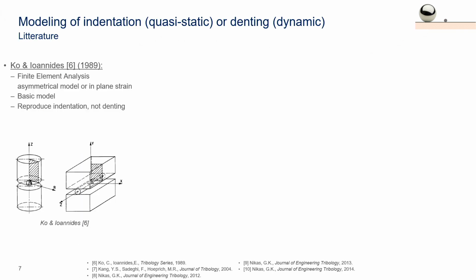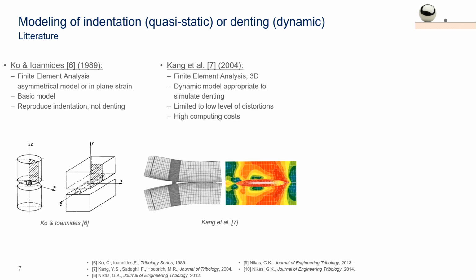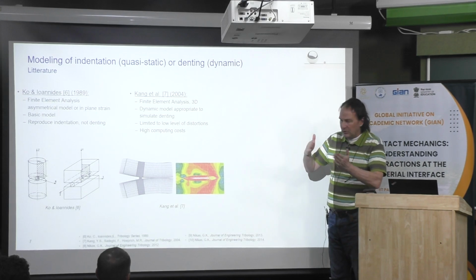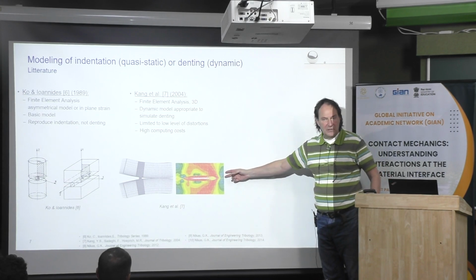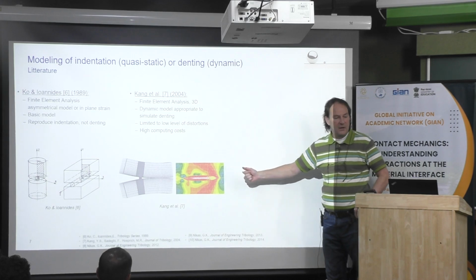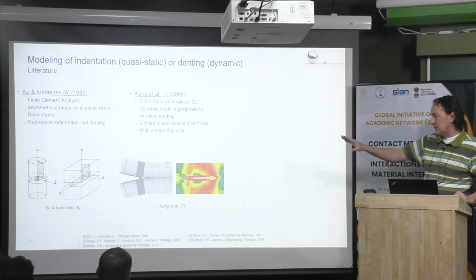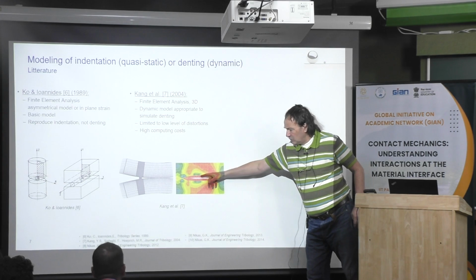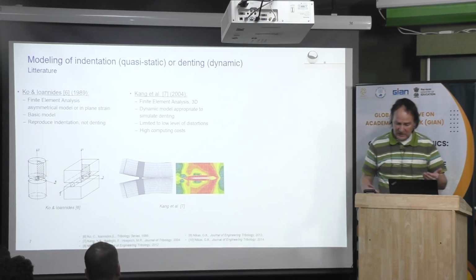Now, modeling of denting. In the past, what has been done was always some finite element model, except for one researcher. The first work is due to Ioannides from SKF. He did that with the finite element method, but it was only in indentation. In fact, there was no dynamic effect. Then a few years later, in 2004, Kang and Sadeghi from Purdue University, working with Hoeprich from Timken, did a model like you can see here, and they were able to compress a dent between two rollers. This is a 3D approach, and a dynamic approach because you can consider the dynamic effect here. It was the first attempt, and it was quite nice. The idea was working. However, you can see that the particle is not too much deformed. It was only in pure rolling, but it was the first step to solve the problem.